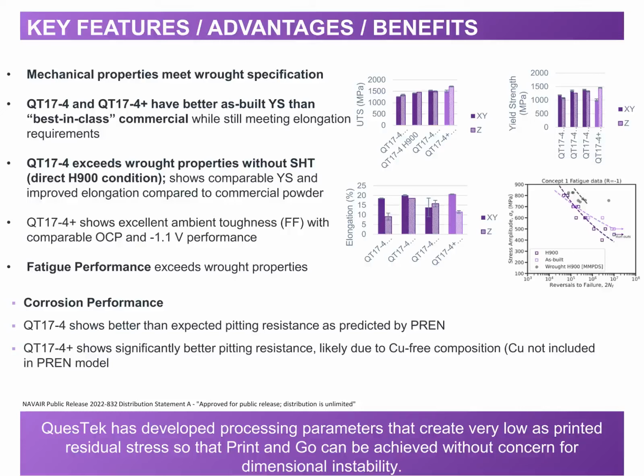QuesTek is able to demonstrate via testing and validation the key features and benefits of the 17-4 novel alloys. So both alloys have better as-built yield strength than commercial 17-4. They both exceed the properties without post-heat treatment on yield strength and elongation. It also shows excellent ambient toughness, and the fatigue performance shown on the right-hand curve exceeds the properties of wrought